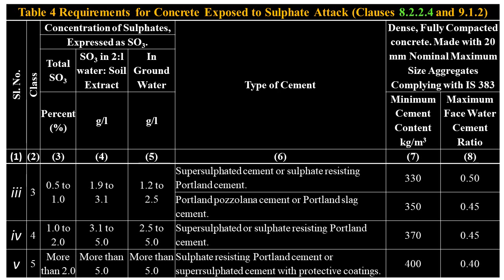Type of cements: Portland pozzolana cement or Portland slag cement. Minimum cement content, 350 kilograms per cubic meter. Maximum free water cement ratio, 0.45.